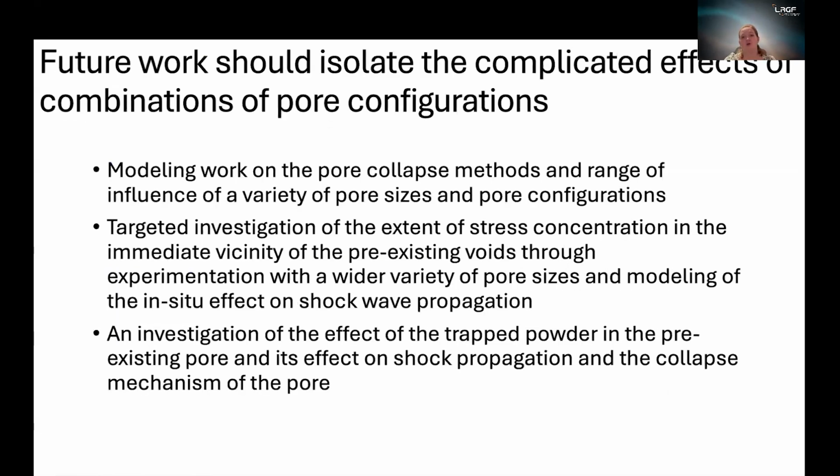So future work should focus on isolating the complicated effects of combinations of pore configurations. So more modeling work on the pore collapse method and range of influence would be particularly valuable, as well as a targeted investigation of the extensive stress concentration in the immediate vicinity of the pre-existing pores. So especially looking at that 500 micron pre-existing pore, where that damage is so concentrated around it that it's hard to isolate after the experiment. It would be helpful to have modeling and more isolated experiments specifically looking to investigate this stress concentration.